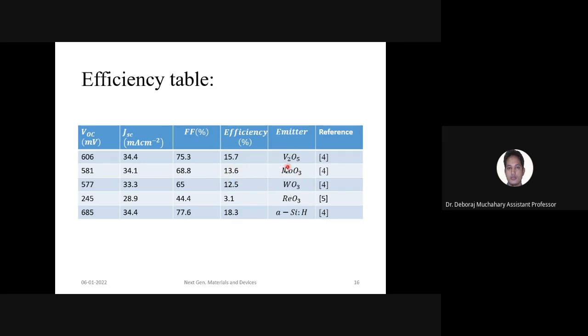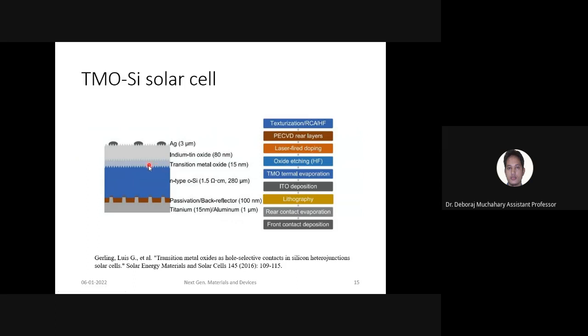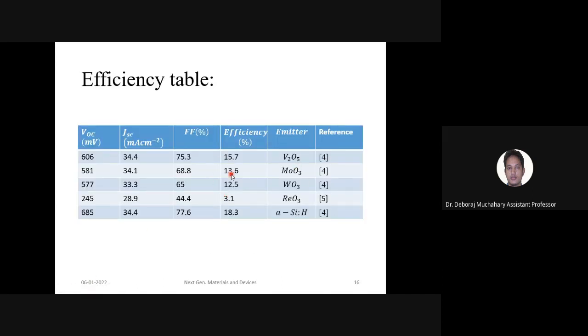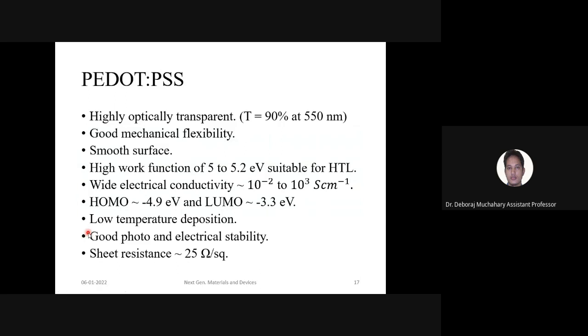If you're interested, you can do some work on minimizing interface recombination at this heterojunction. By putting in some new layer or some technique to reduce this interface recombination, maybe the lagging gap in efficiency may be compensated, or it may be boosted higher. So these are the problems in transition metal oxide based heterojunction solar cells. I'm not discussing the others, like zinc oxide, because their efficiency is low, and the reason is their electrical conductivity. There are lots of research papers on developing the electrical conductivity of materials like zinc oxide and tin oxide.